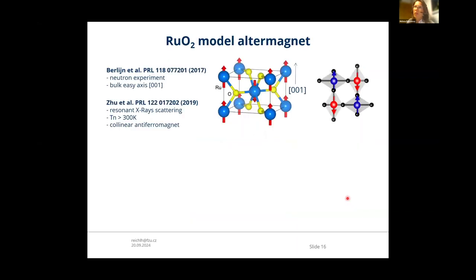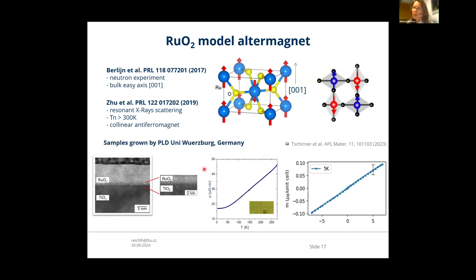So the ruthenium dioxide, as Roser nicely summarized, is now used as a model cartoon system. However, in the realistic realization of the films, we are not sure if these experiments are to be trusted. And this was also something which we wanted to test on the samples, actually from Simon Moser from Würzburg. So the samples which Simon grows are indeed of very, very high quality.